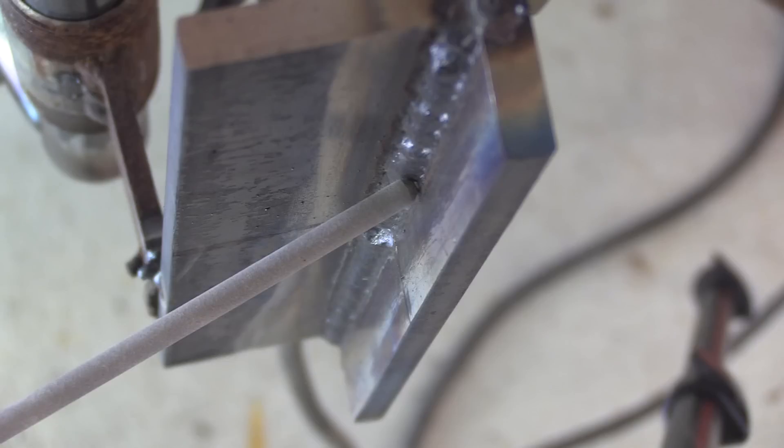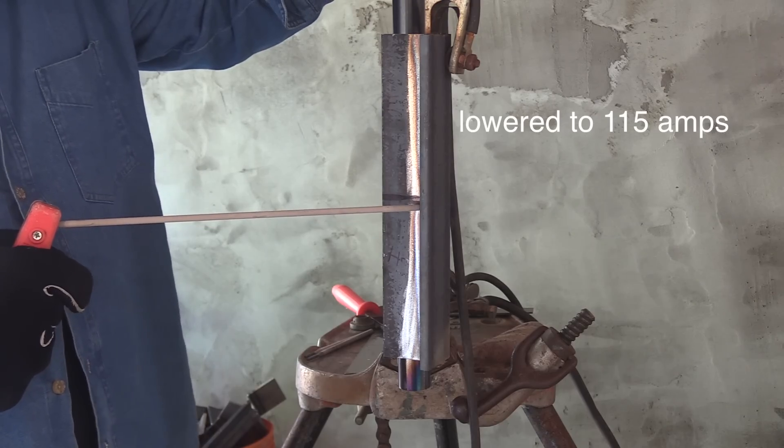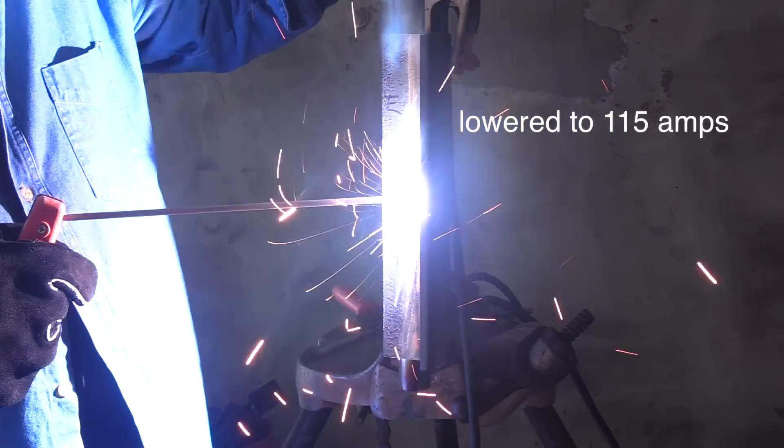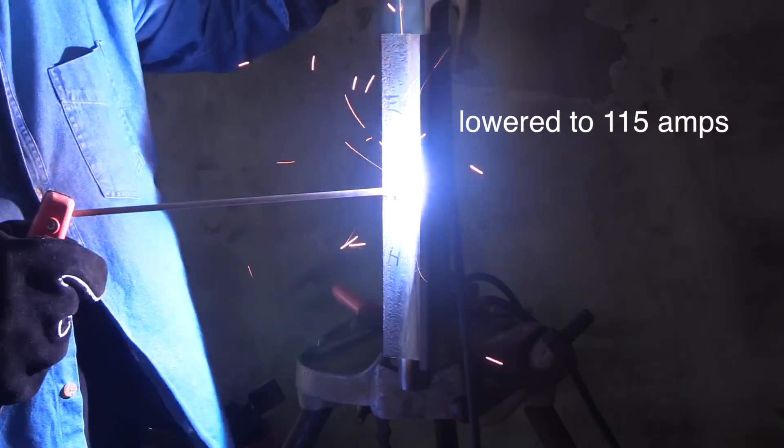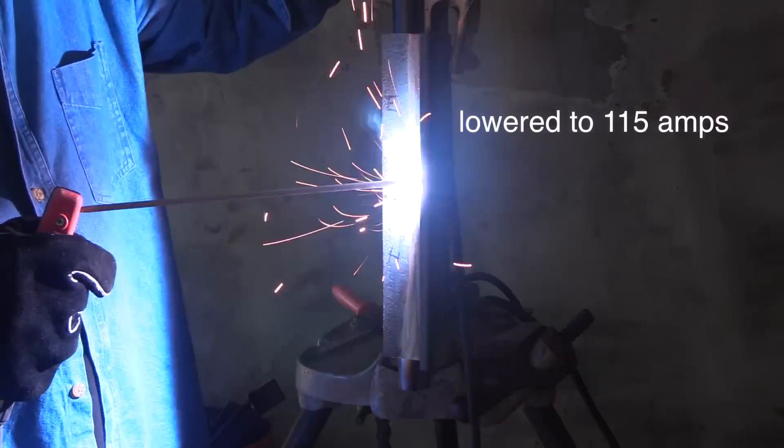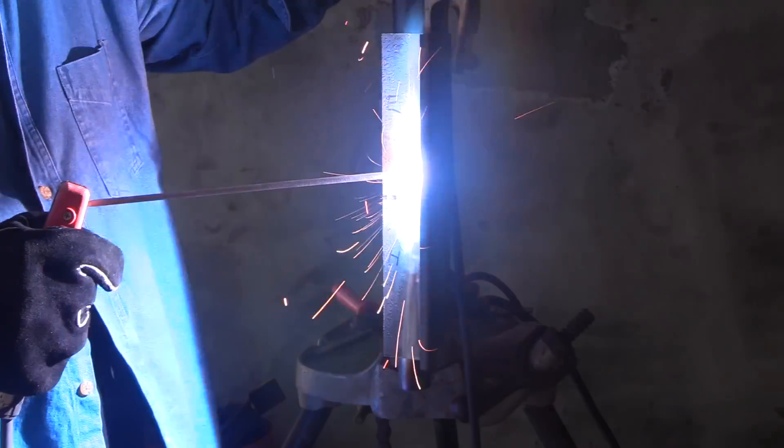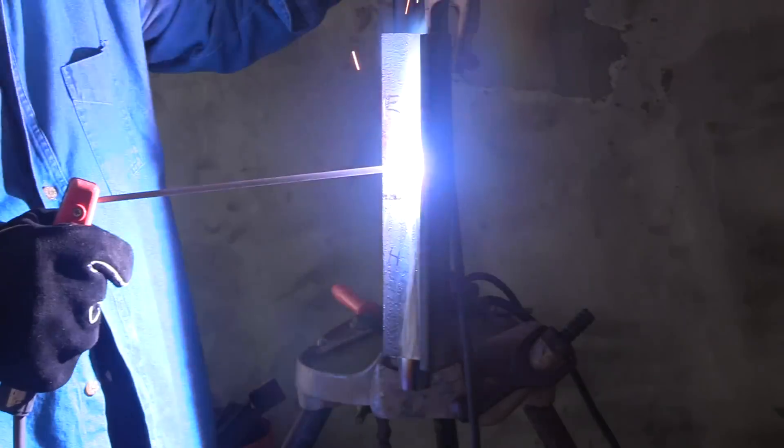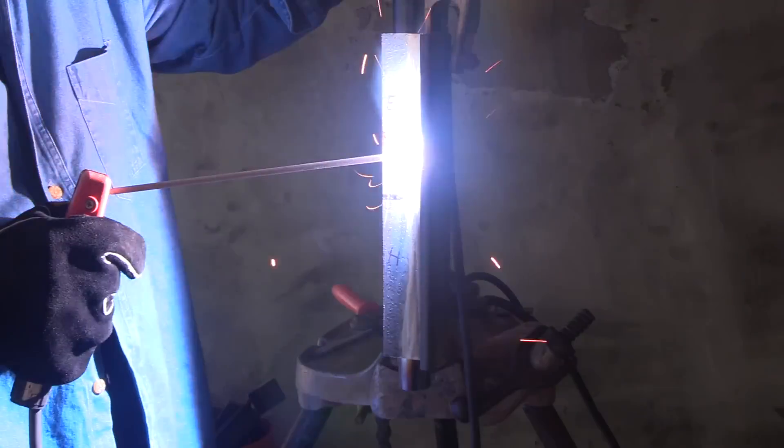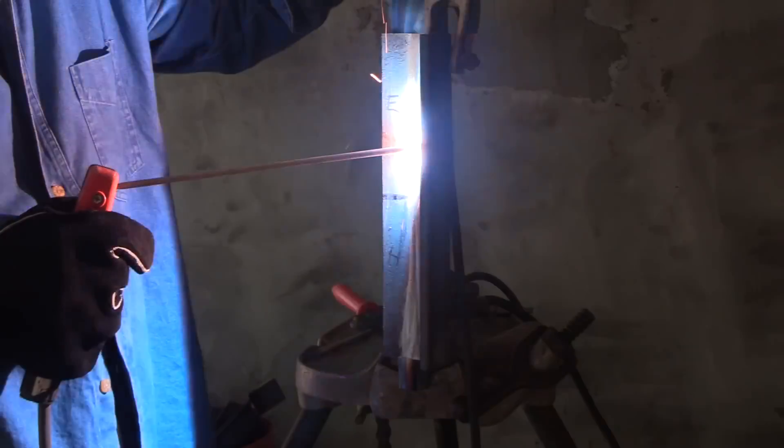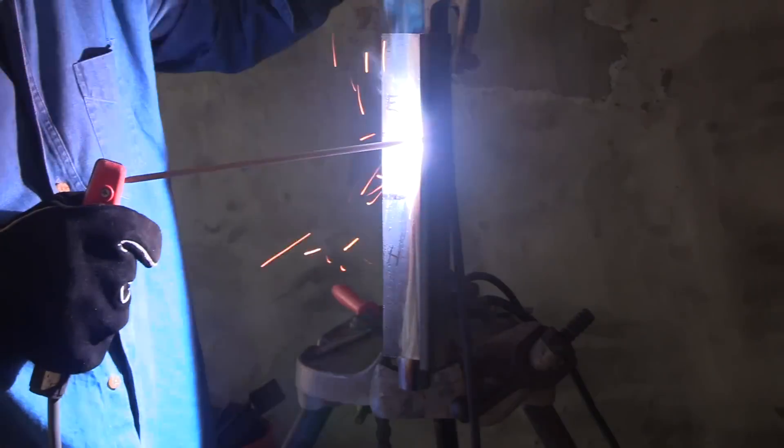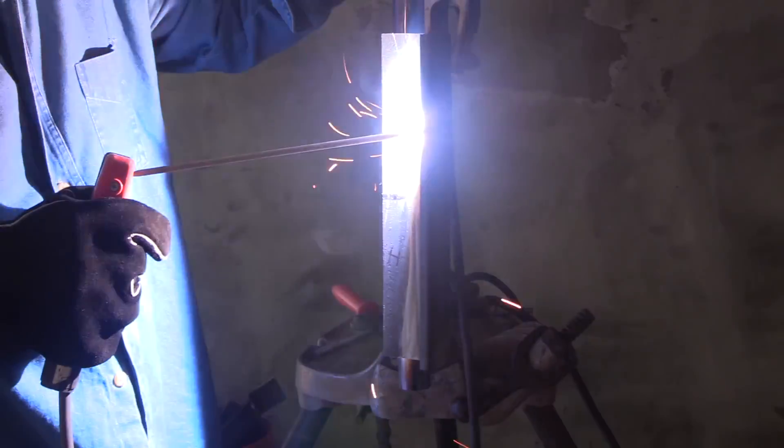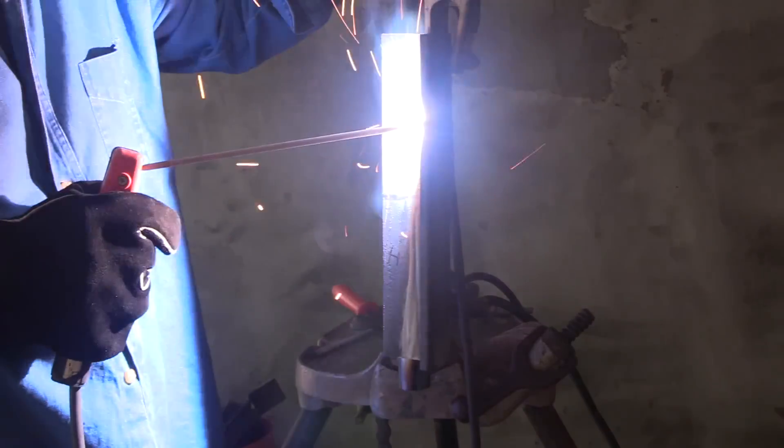So for this next bead, I'm going to use this kind of angle. I'm slightly favoring the right hand side so that I'll help prevent undercut. So the first pass I welded at 120 amps, but now things are warming up a little bit, so I just knocked it down 5 amps to 115. Notice I'm starting out here pretty much just a slight push angle. I started out actually closer to 90 degrees. As I go forward, I get a little bit more of an angle, but the good thing is if you hold a tight arc, electrode angle is very forgiving.